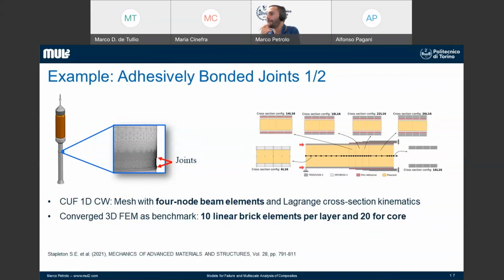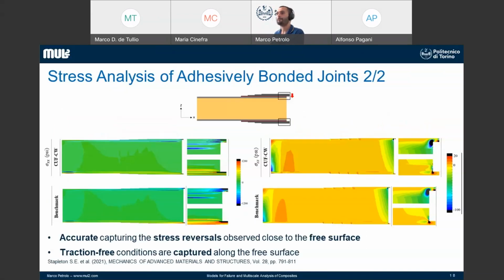Let's see just a few numerical results. This is a typical assembly for a space structure. In particular, we are interested in this area in which we have a joint between 2 different composite parts. On the right, we have a cross-section of what we have on the left. As you can see, there are different materials with different geometries and a lot of geometrical discontinuities. This is just an example to let you see how complex the stress field can be around that area. And you can see the stress field in these 2 pictures.